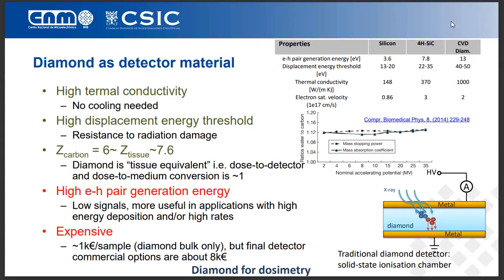The atomic number is very similar to tissue. This makes diamond so-called tissue or almost tissue equivalent, which means that the conversion between the dose to detector and the dose to medium, in this case tissue, is almost one. You can see the plot on the right that I got from somewhere, and this is important for radiotherapy planning.